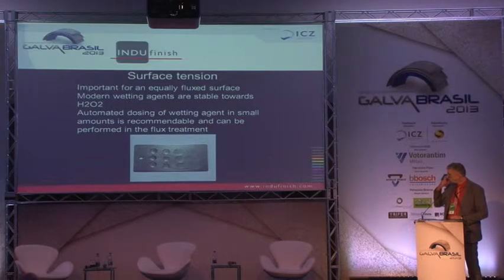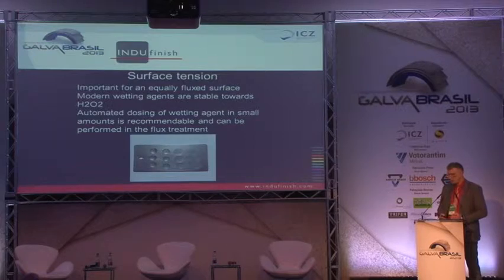Surface tension. It's important that your flux fluid has the lowest surface tension, because in that way it will crawl around your product. And this flux layer, this salt layer, has a large effect on the quality of the buildup of your zinc layer. So make sure that the surface tension is very low.